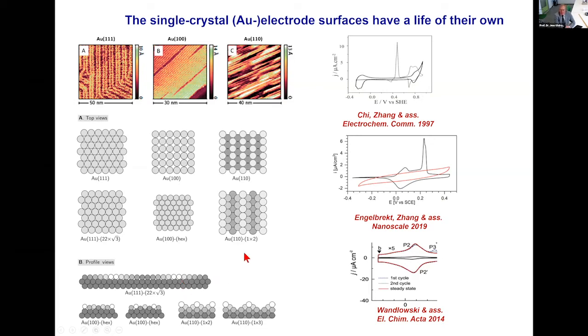There's also the life of its own that can be seen electrochemically, because at certain potentials, reconstruction is lifted. That can be at certain potentials or on anion adsorption. So that is very specific for the different electrode surfaces. You can see 111 and 100, and here 110. So if we observe strange electrochemical signals somewhere unexpected, it is not necessarily Faradaic signals. It can be capacitive signals, and they can be very sharp if a phase transition is involved.